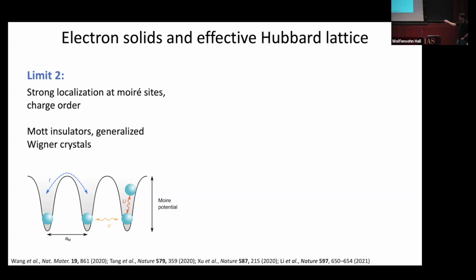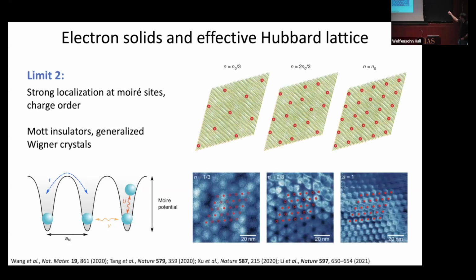And in this sort of scenario, just like I described in the introduction, you can get strong interactions where, for example, if you have one carrier per Moiré unit cell, then you have what is often termed a Mott insulator, where you have one carrier per site, and the double occupancy is basically forbidden by some large U. But because of this extended range interaction V, you can also get interesting phases at partial filling of one of these Moiré bands. For example, if you have one Moiré site out of every 3 occupied, then because of the long range repulsion, you want to keep the carriers as far apart from one another as possible. And so you form what are known as generalized Wigner crystals.